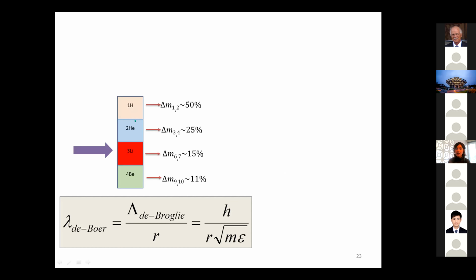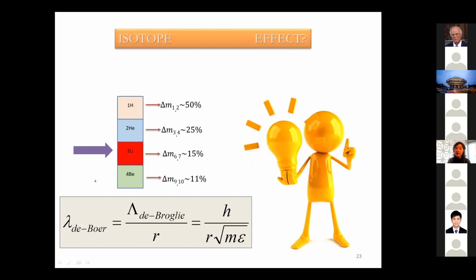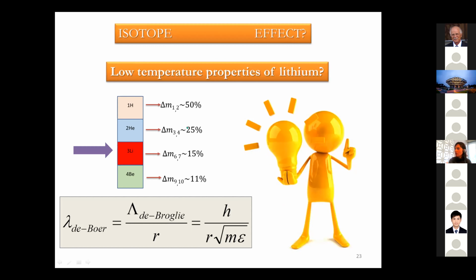And this is where these very low Z, light elements are wonderful, because the difference between their isotopic masses is huge, like 15% in the case of lithium 6 and 7. So we can rely on that, because the isotopes of the same material should not have very different physical properties. And if we see these huge differences, then we know it's originating from the quantum effect. So that's where I'm going with this from now on. Another thing we are going to do is go to low temperature to minimize the effects of disorder coming from non-quantum contributions, like from the phonons.